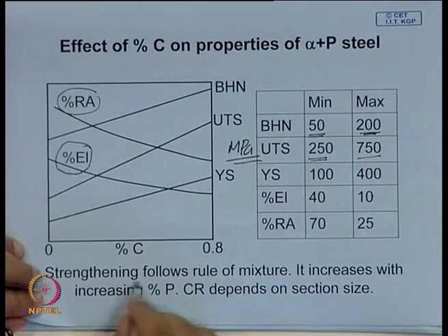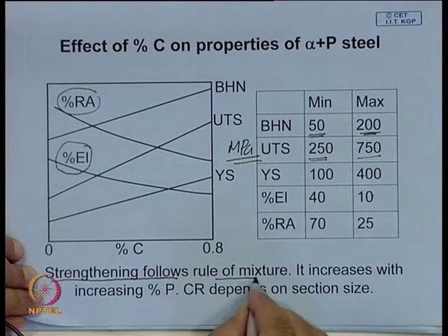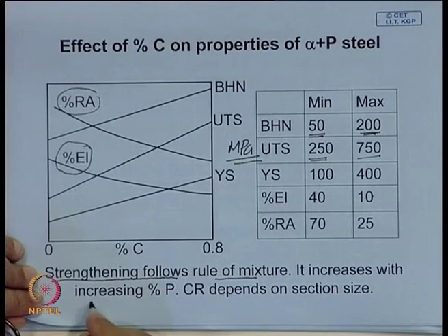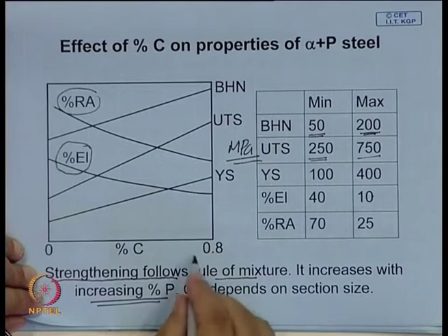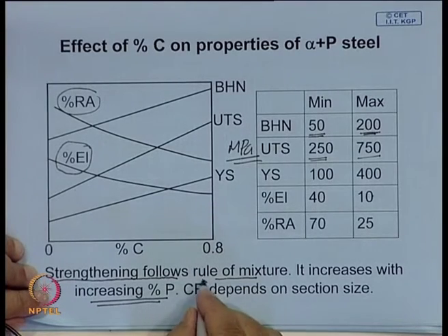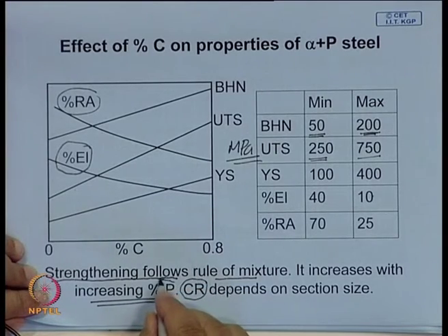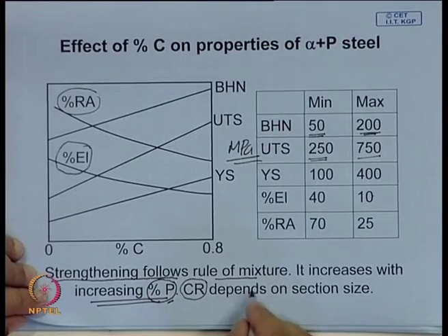Strengthening in these types of grades follows the rule of mixture. If you increase the amount of pearlite, its strength will increase, and by the cooling rate it is also possible to control the fineness of pearlite. If you increase the cooling rate and the pearlite is finer, then also the strength will increase.